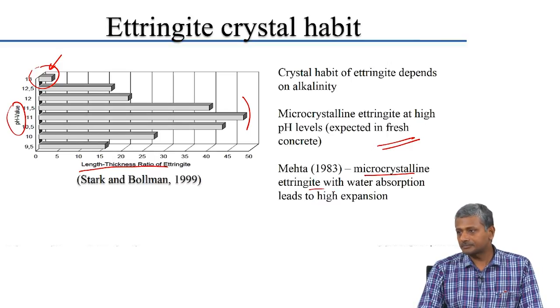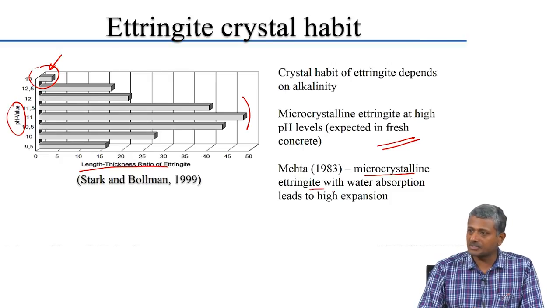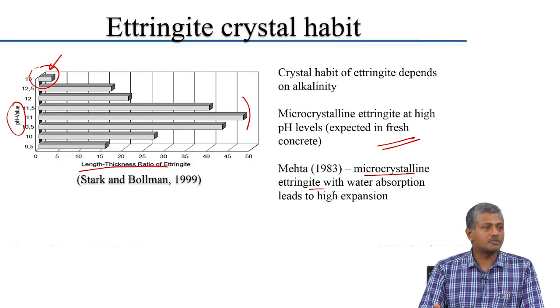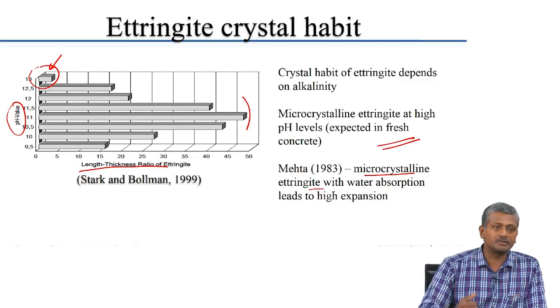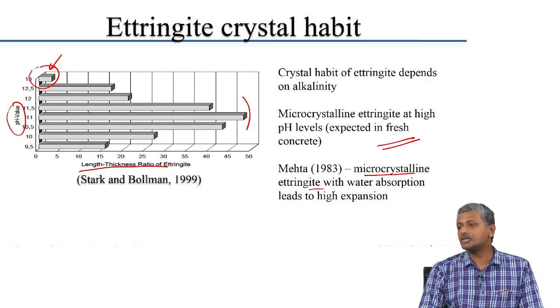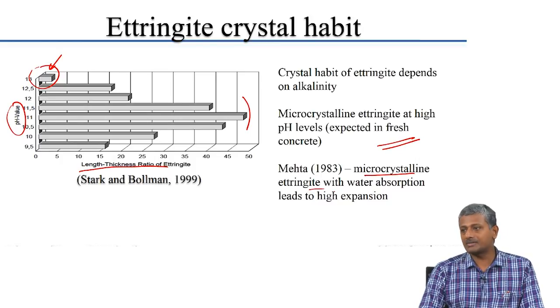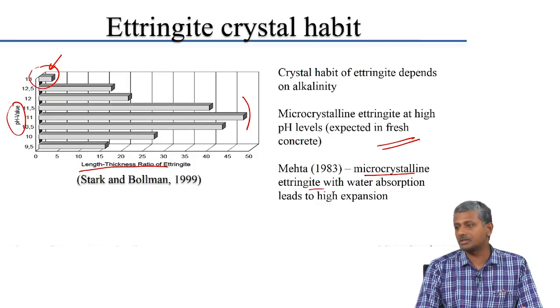This explains to a large extent why we do not really see expansions happening in field-based specimens. In lab specimens we see very high expansion, but in actual field performance, which is accompanied by continuous replenishment of the attacking solution from groundwater recharging, plus the presence of other ionic species that may bring down the pH of the surrounding solution, the ettringite forming may not end up being as expansive as what forms inside the system in a regular immersion condition.